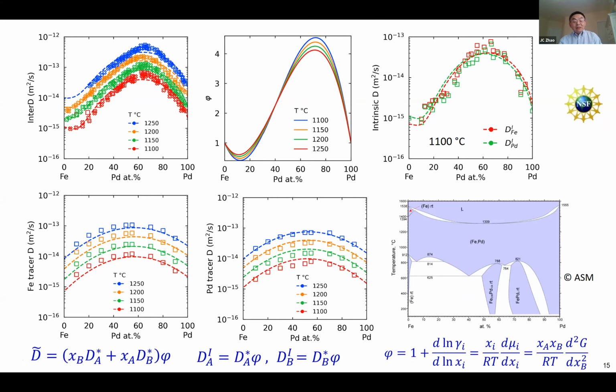So you can see that the impurity diffusion coefficient behaves very regularly. There's no up and down. It's easy to fit with a parabolic constant. But the interdiffusion coefficient and the intrinsic diffusion coefficient can also have a thermodynamic factor in it. So that's how the ups and downs in the curve come from.